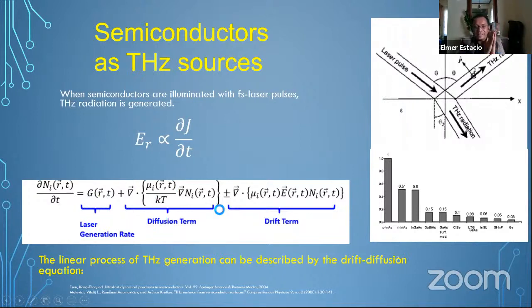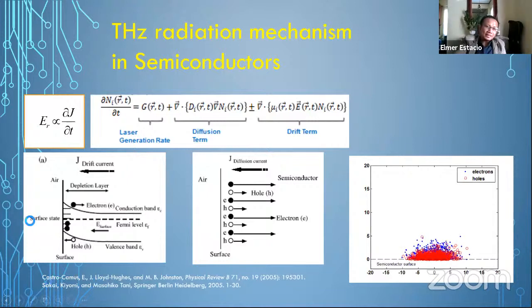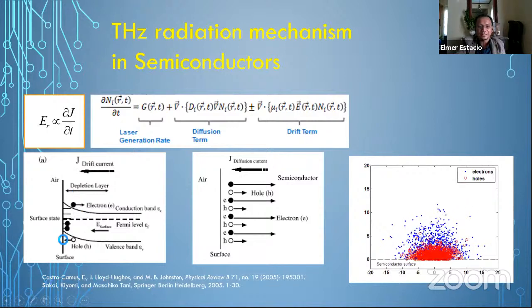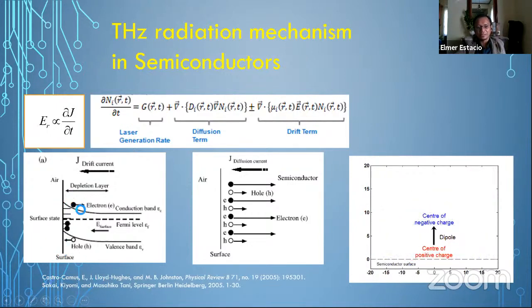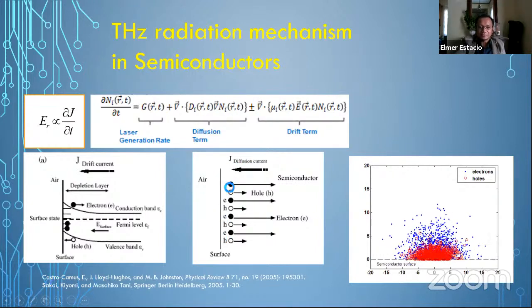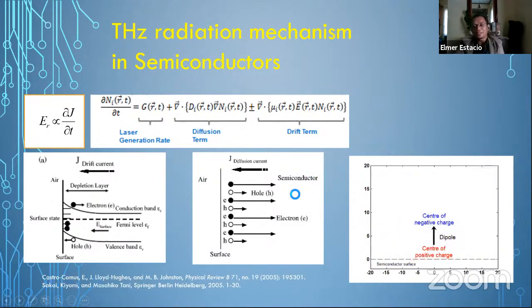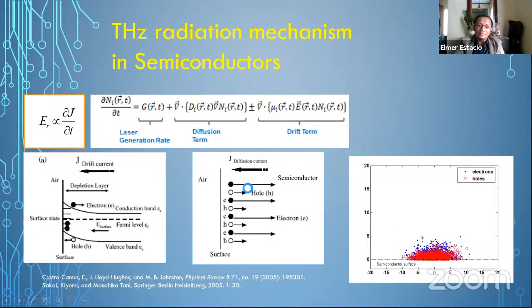The diffusion term is a contribution to the terahertz radiation by simply a gradient in electron density from one region, presumably the region where the semiconductor is illuminated, to the region where the semiconductor is not illuminated. And the drift term is due to the electrons being under the influence of an electric field and thus undergoing transport. So a terahertz radiation mechanism in a semiconductor may be characterized by drift, wherein here is the energy band diagram of a semiconductor. Electrons may undergo transport due to the electric field. And since in some cases electrons near the surface would travel to the bulk region at a faster rate because electrons are lighter than the holes that they leave behind, this would generate a net current that is depicted here in this cartoon, where the net separation of the electrons and holes would generate, again, this time-dependent current.